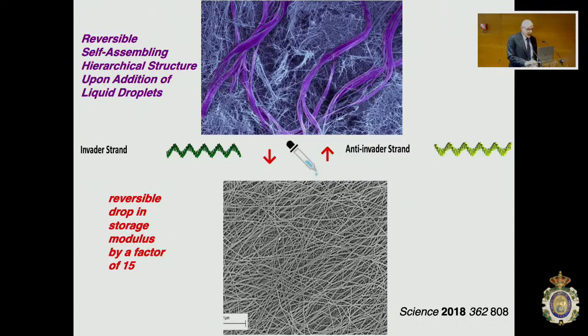That was very exciting, and in fact, you can see at the bottom that when we disassemble the DNA, which is what drives the formation of these bundles and what causes the molecules to walk, is their driving force to create this pairing among the bases. When you disassemble, as you see at the bottom, the purple regions are completely gone, by just putting a drop of a molecule in water on top of it, so that it will cause the disassembly of the Watson-Crick pairing. And that has a mechanical consequence.